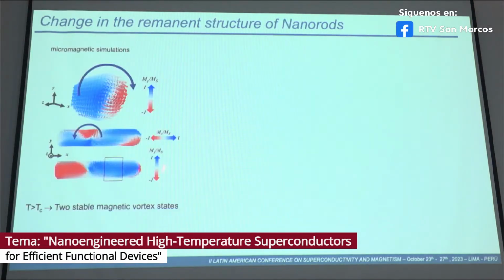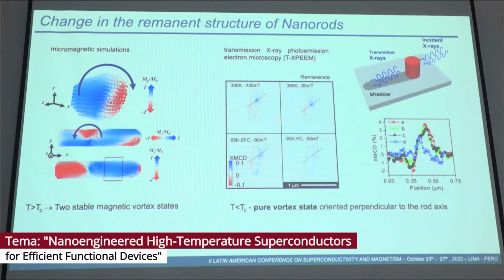And this would be a micromagnetic simulation of what would happen in one rod. What we have is the stabilization of two vortex states, one with the axis perpendicular and the other one with the axis parallel to the rod. And when these rods are embedded inside of the superconductor, these are the magnetic imaging of the magnetic domains of the rod, measured when the rod was magnetized above Tc at room temperature and with zero field cool below Tc.